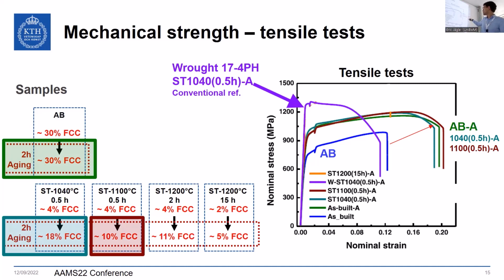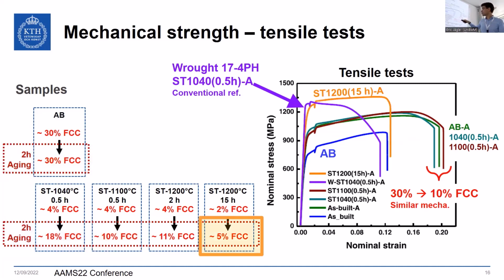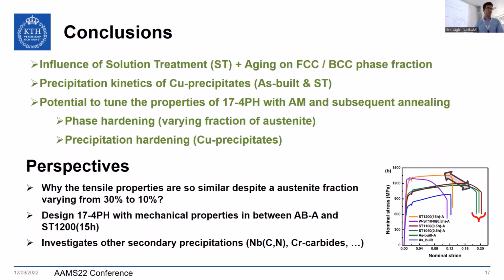Interestingly, for these three alloys, we have very similar tensile test results, even though the FCC fraction varies from 30 to 10%. Of course, a bit surprising. And for this final highest temperature solution treatment alloy, we have very high yield strength, so high, similar to the wrought material, and relatively high, maybe even a bit better, ductility. What is interesting here is that we could tune the mechanical properties through this process, depending on whether you want high yield strength and lower ductility, or lower yield strength and higher ductility for your alloy, which is possible thanks to this additive manufacturing process.